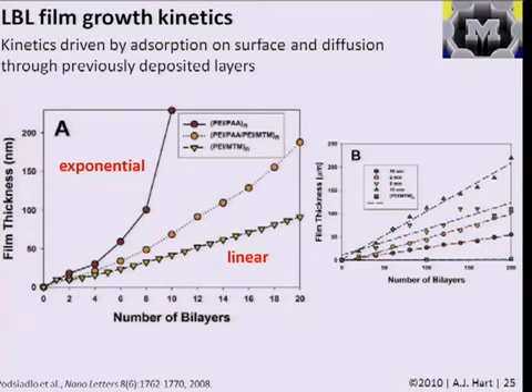And what I want to say here is that in some cases you see a linear growth kinetic, which means the thickness is linear with the number of bilayers or with time. And in other cases, at short numbers of layers, you see an exponential growth kinetic. What this means is that when you have a pre-existing film, say it has 5 bilayers, and you put it in the solution of the next component, not only do you absorb the new layer, the new half of a bilayer, but also the component that's in solution diffuses into the existing film and swells the pre-existing layers.